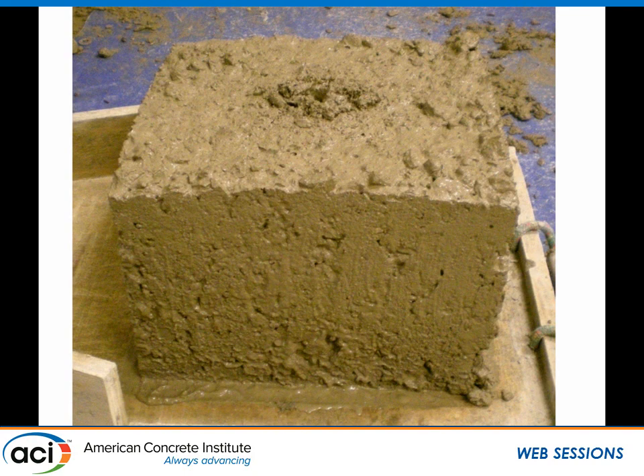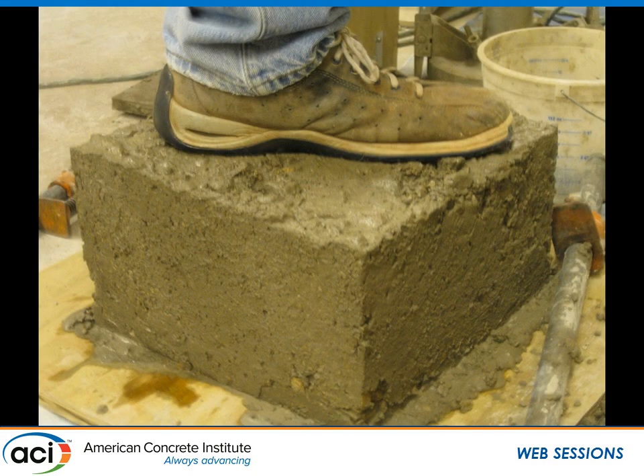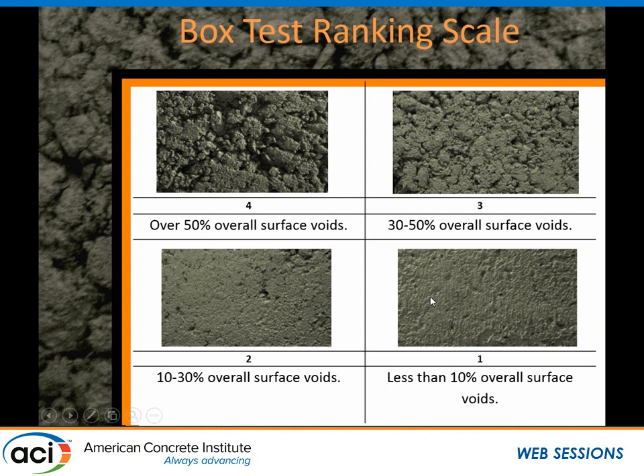The best concretes have to surpass this next test. That's me standing with one foot on top of the concrete brownie 30 minutes after it's been placed. That 30-minute-old concrete holding me on top of it — that's how much packing we've gotten inside there. It's still not edge slumping. We can look and inspect these voids. The way we rate mixes, we use a graphical or observational technique.